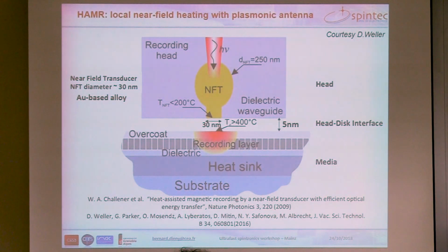So as I said, since we want to heat locally, we cannot just focus the laser directly on the media. The laser is focused on a near-field transducer. This is a plasmonic antenna, made of a gold-based alloy, because gold is very good for plasmonic emission. And this is the shape of this plasmonic antenna, from Seagate here.